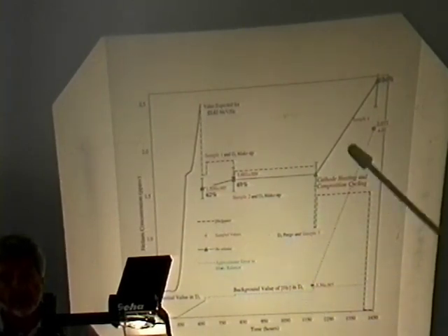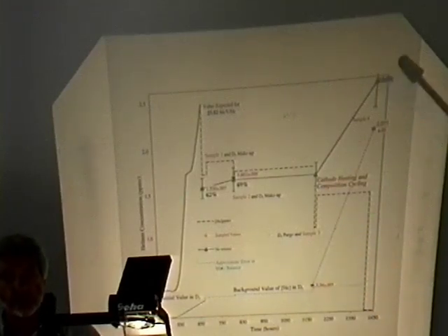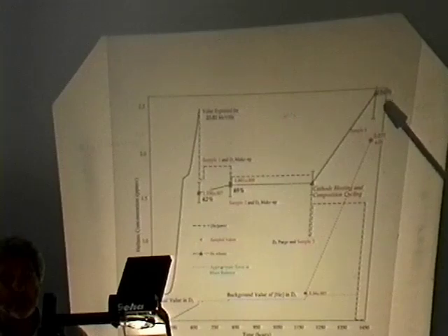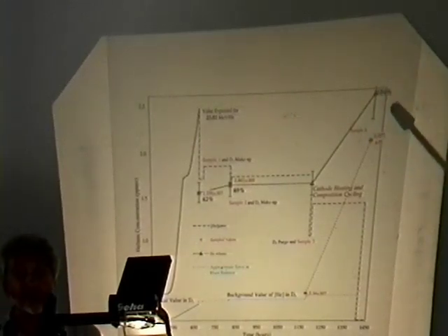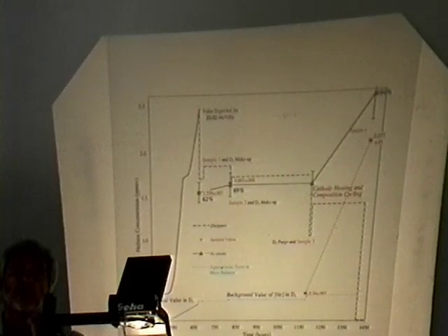To make a long story short, after a considerable period of exercising this cathode, we made another helium-4 analysis, and if you do your mass balance and do your math correctly, which I didn't do in my initial publication, you find that you achieve 104% plus or minus 10% of the expectation value. So quite clearly, the helium-4 is present.